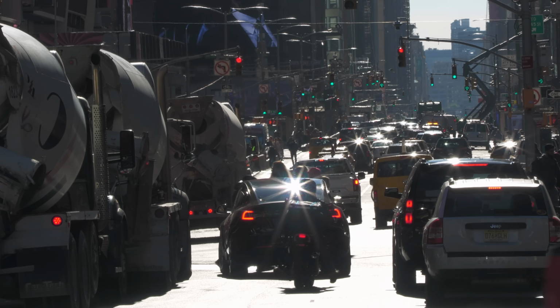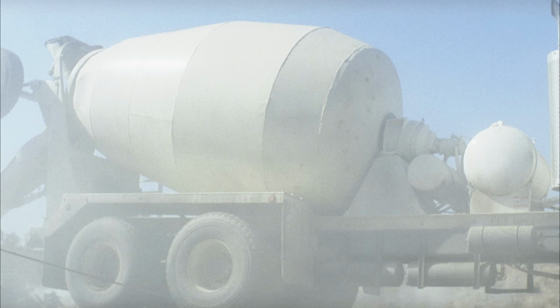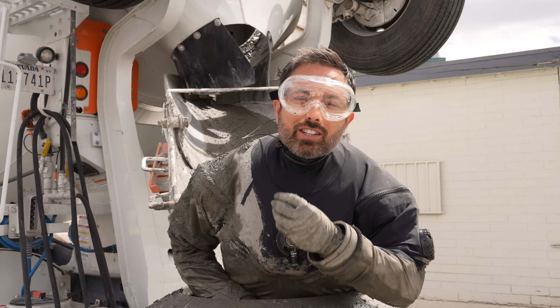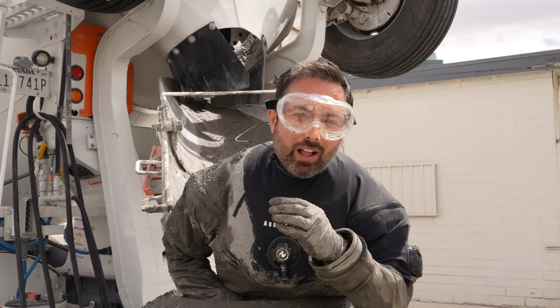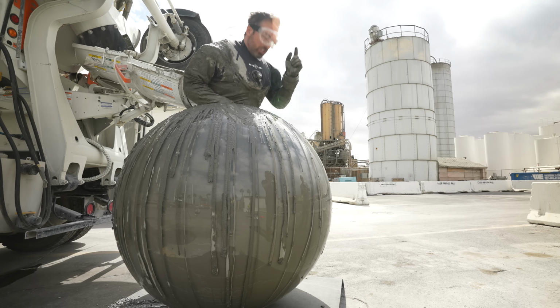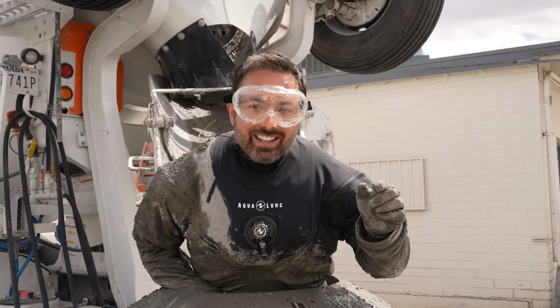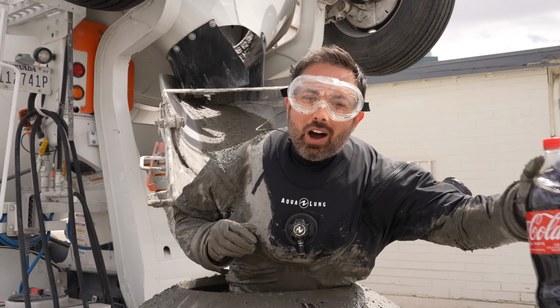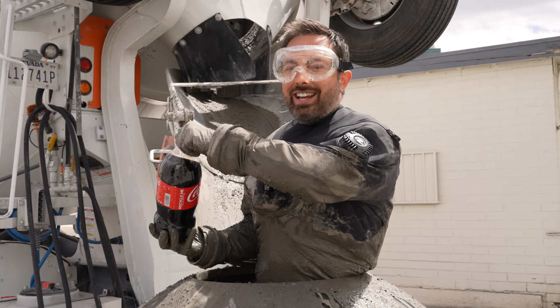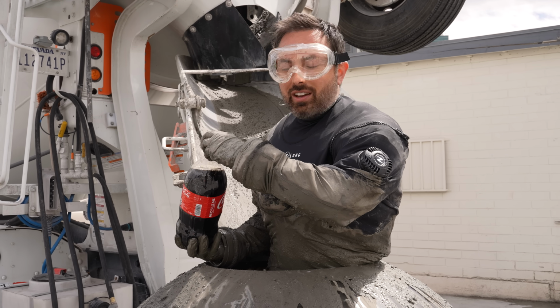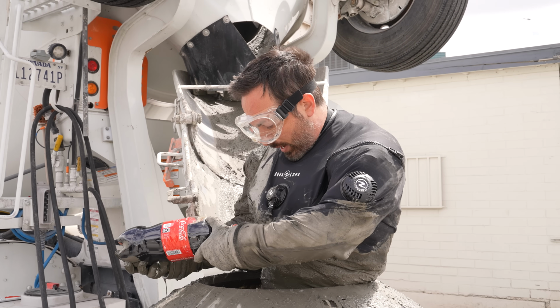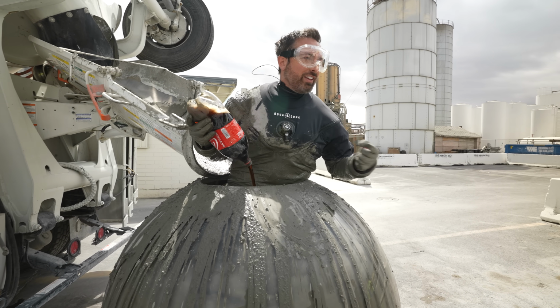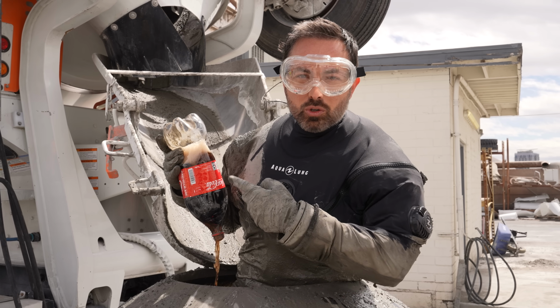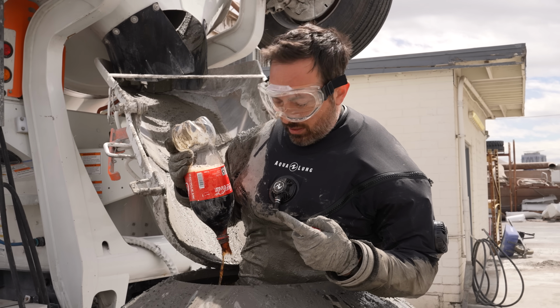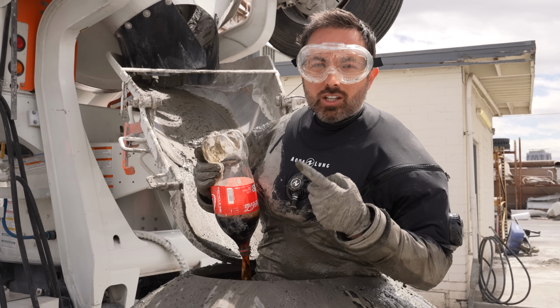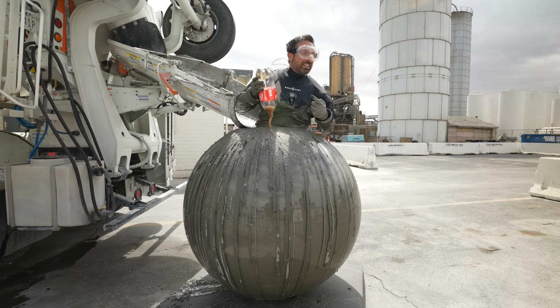But what happens if the truck breaks down, or there's a traffic jam, or something breaks? Then at times, concrete does harden inside the drum of these trucks, and that is a terrible outcome. But there is one thing you can do to slow the concrete down from setting, and that is to add some regular pop, like Coke. The sugars inside this Coke actually prevent the setting up process from happening, and that can buy you a few hours. So apparently these truck drivers, they drive around with a few 2-liter bottles of pop inside their cab, and so they can dump it in their load if they have to prevent it from setting up. So hopefully that means I'll get out okay too.